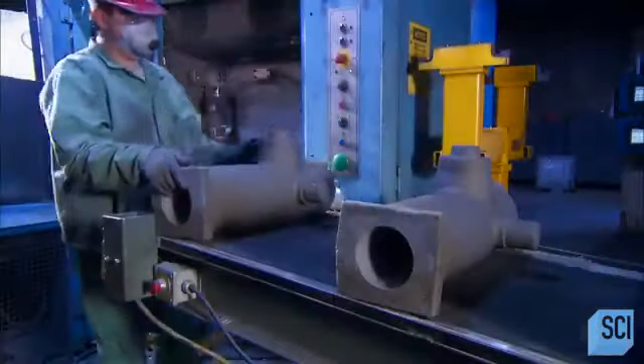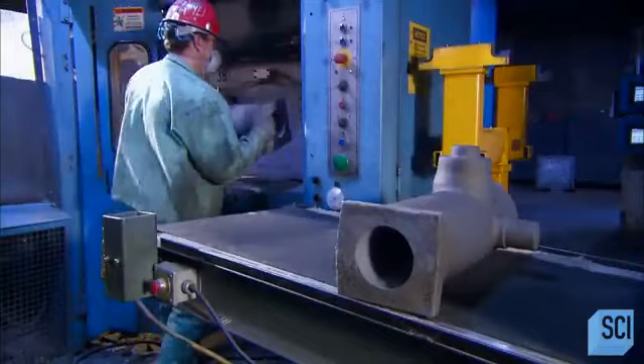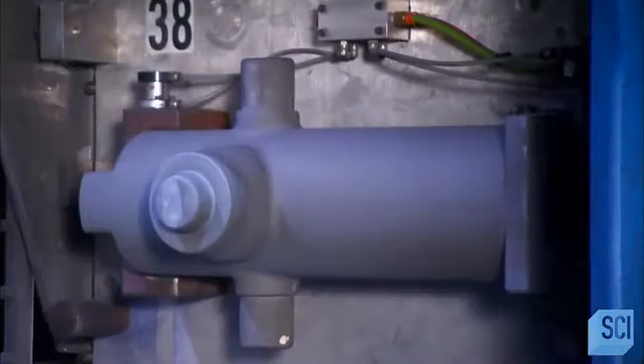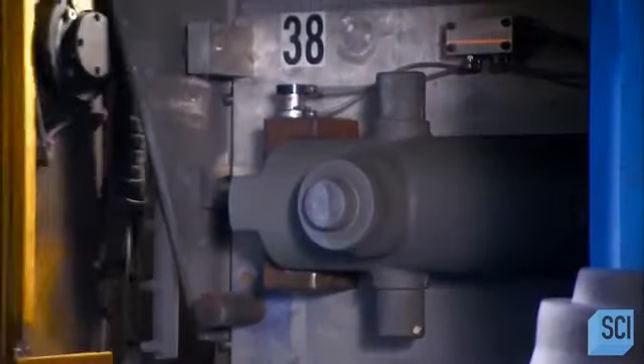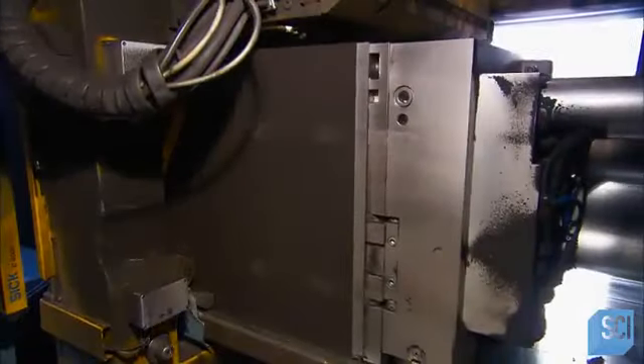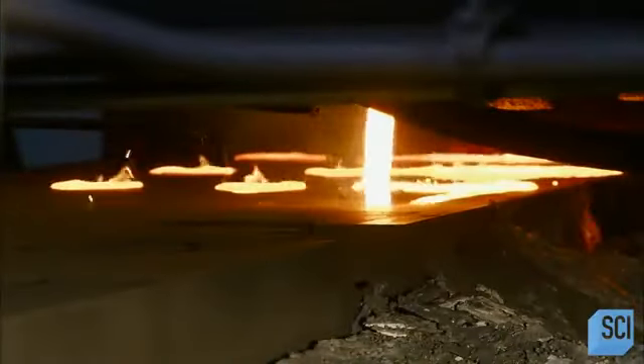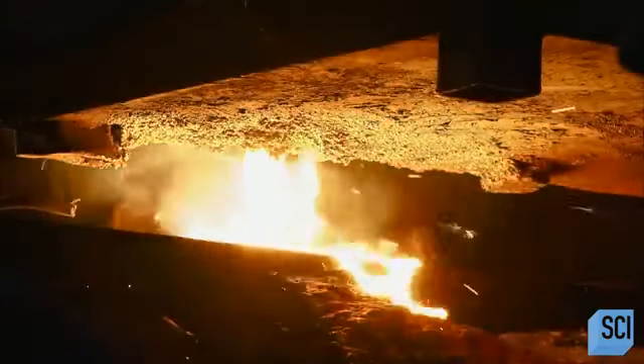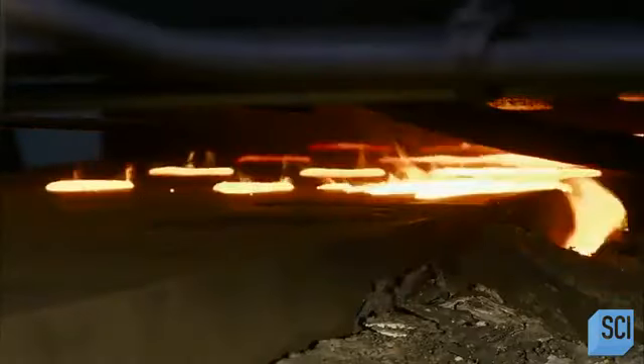To cast the hydrants, workers first make two-part molds by compressing a mixture of sand and bonding materials. One part, called the mold, forms the hydrant's exterior shape, while the other part, called the core, forms the interior shape. An automatic core setter positions a core in each mold. Then, a conveyor advances the mold under the pouring box, which fills the cavity between the mold and core with molten iron.